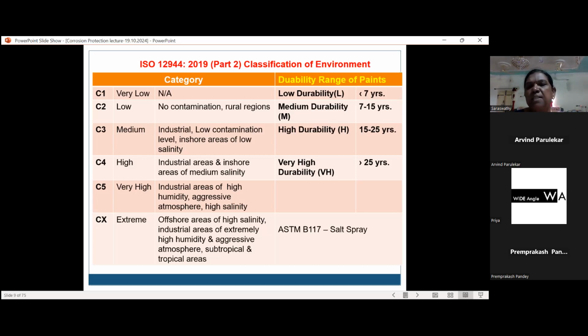So if it is passing more than 1440 hours, the paint will last for 7 to 15 years in the highly aggressive environment as per ASTM B117. So this is the durability of the paints we have tested. We can't guarantee any paint with higher durability, but as per the standard, high durability paint will last for 15 to 25 years.